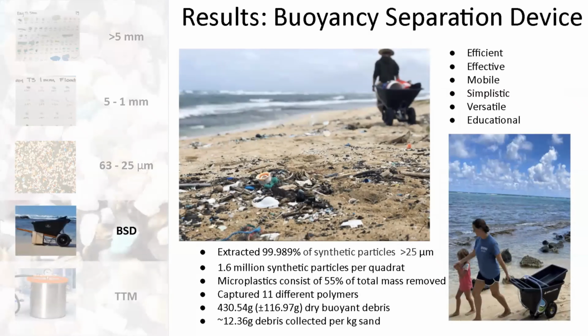So with the buoyancy separation device, again, this is an open source tool that we created to allow anyone to be able to remove this material. So it's great for its practical application in cleaning up our beaches, but also an effective tool for us analyzing scientifically shoreline marine debris pollution. From using this method, we found that it is 99.99% effective at removing this material, and that per quadrat, we're removing, again, over 1.6 million pieces in this process, and that on Oahu shores, 55% of our mass is just microplastics.